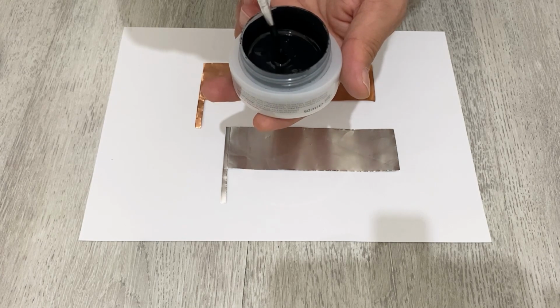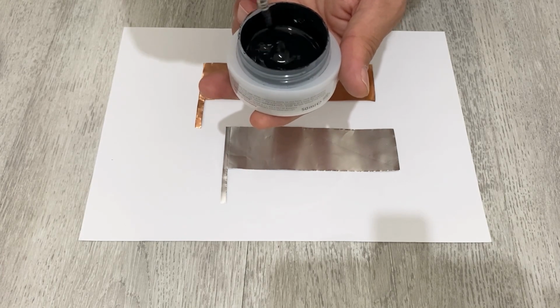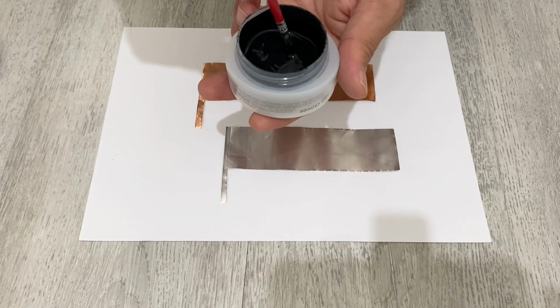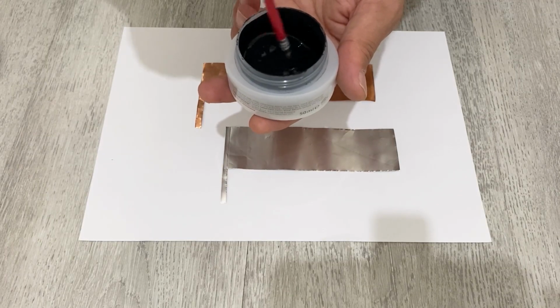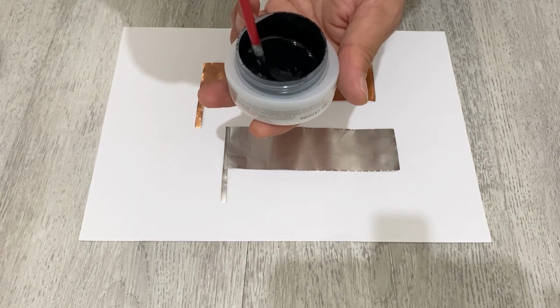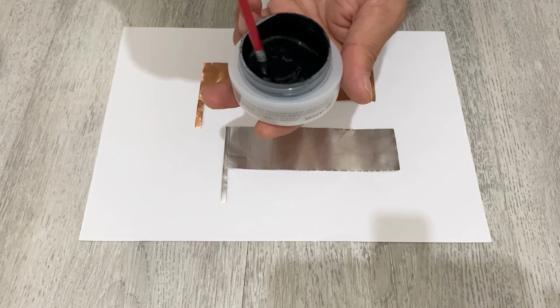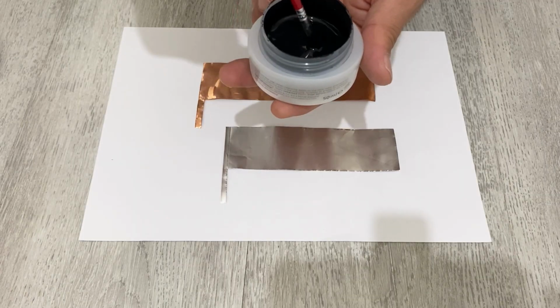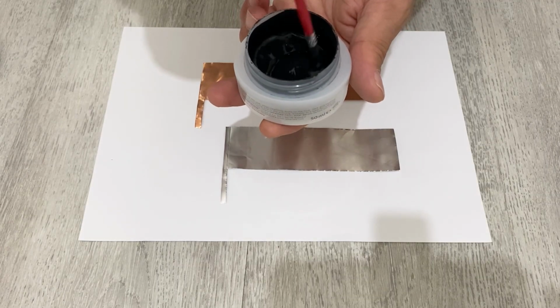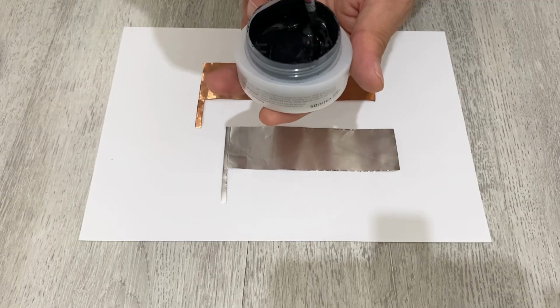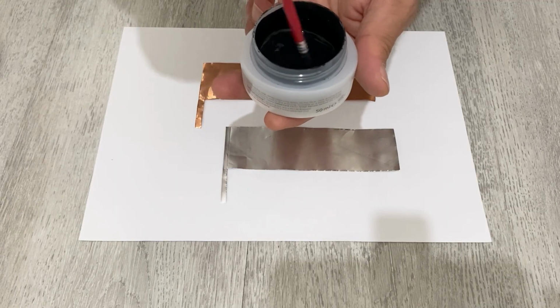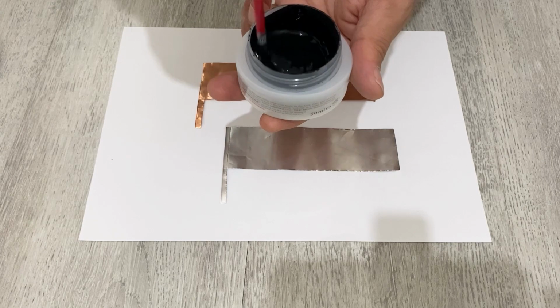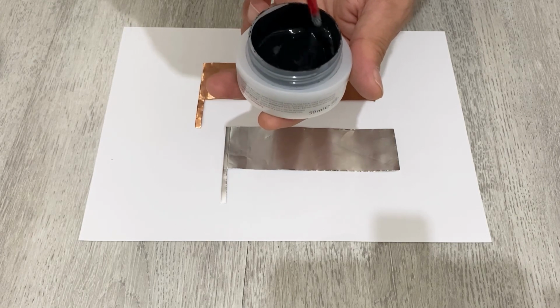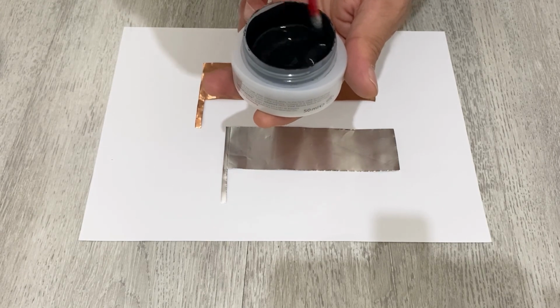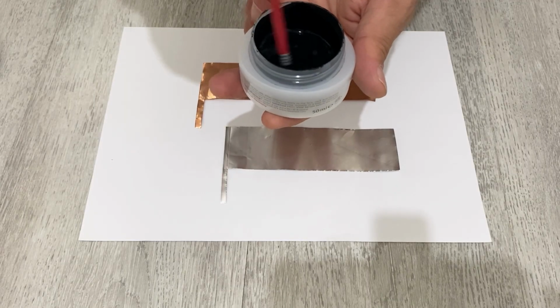You need to put 20 grams of ultrafine graphite powder, 2 or 3 grams of sodium silicate and 20 or 25 milliliters of deionized water, and mix it very well to make this slurry active material. Now I will paint my copper foil with this graphite active material. Before I apply the active material, I need to mix it very well. Okay, now I'm going to just paint my copper foil.